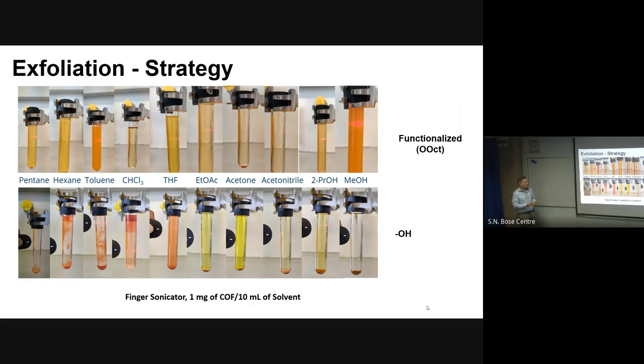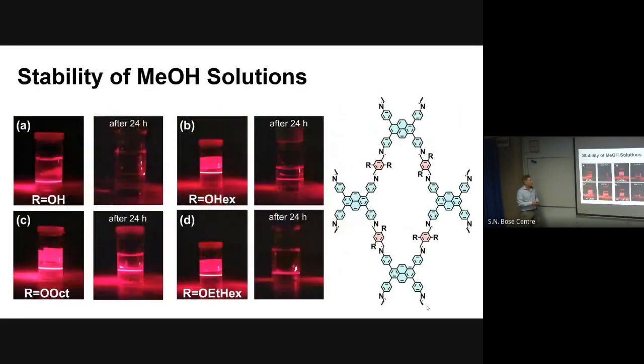Which means they are not so easily dispersed. From this, we decided to use ethyl acetate and methanol as the solvents to carry out our exfoliation studies, because certain factors from the AFMs that we took pointed us in the direction that these are the most efficient solvents for the exfoliation. Here we have some methanol solutions, and you can see that when we make the solution, we have Tyndall scattering in the OH functionalized material. After 24 hours, we don't see much. Not much is in the solution. With the other functionalized materials, the Tyndall effect is quite strong even after long times of settling.